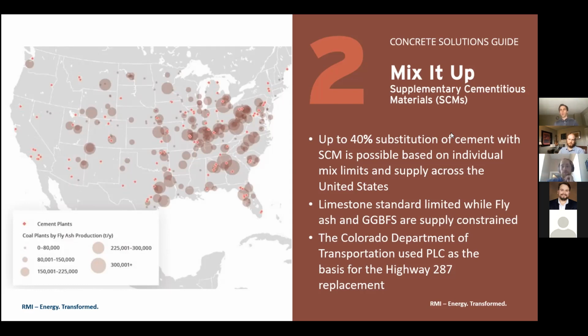So here we're talking about 27 million tons of CO2 per year that could be offset if we could reach that 40% substitution. In terms of those constraints, in order to reach that 40% estimate, we basically used the ASTM limits on limestone, which is 15%. And then both fly ash and slag are supply constraint limited. So in terms of slag, that's a pretty severe supply constraint. There's only a few primary steel mills left in the US, all of them in the Midwest. And so it is regionally quite constrained, and the total volume is not that high, even though it can substitute a large amount of cement in a given mix.